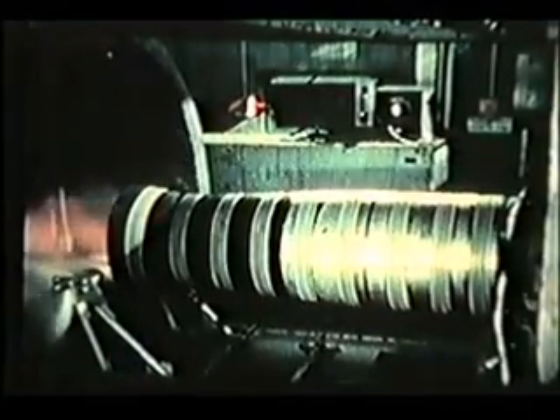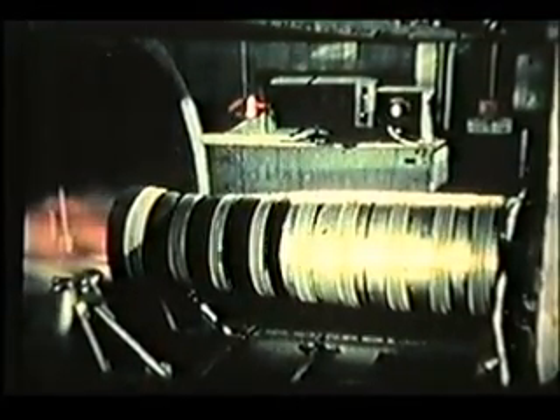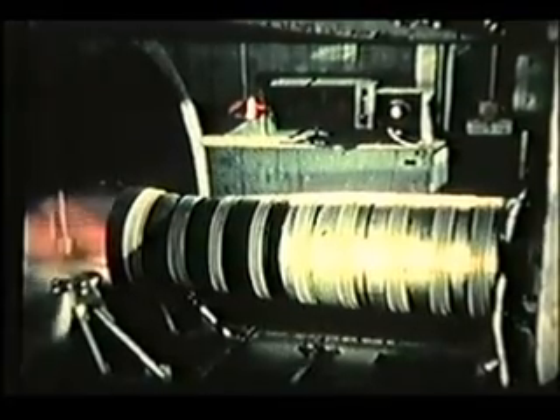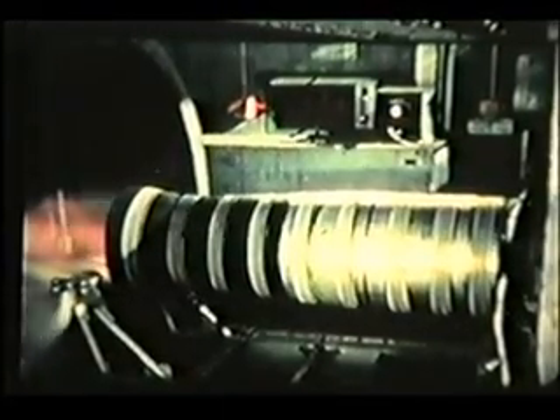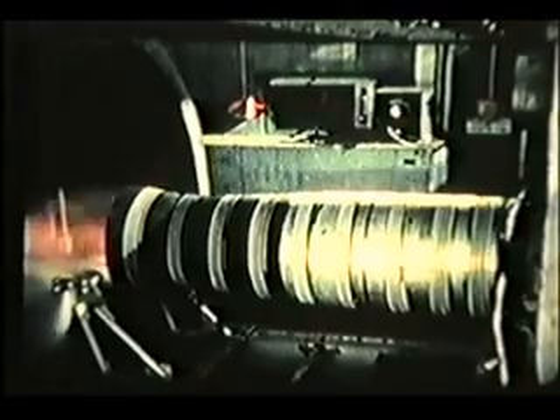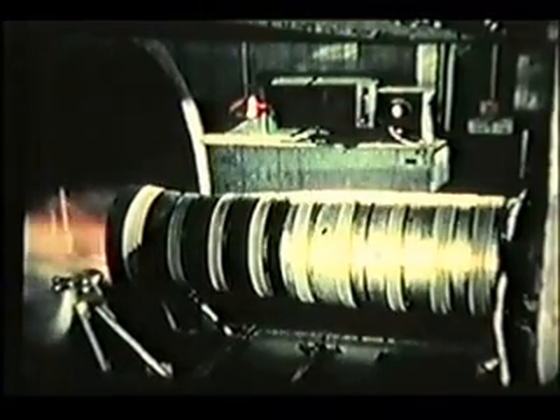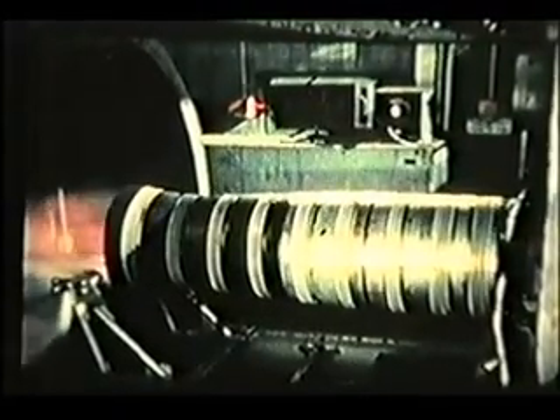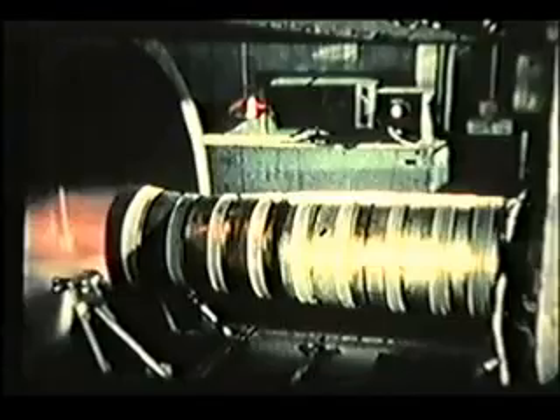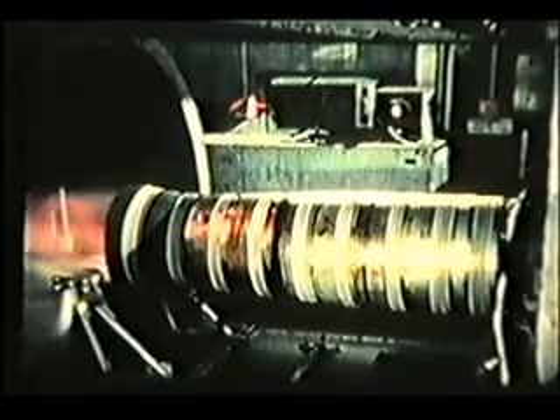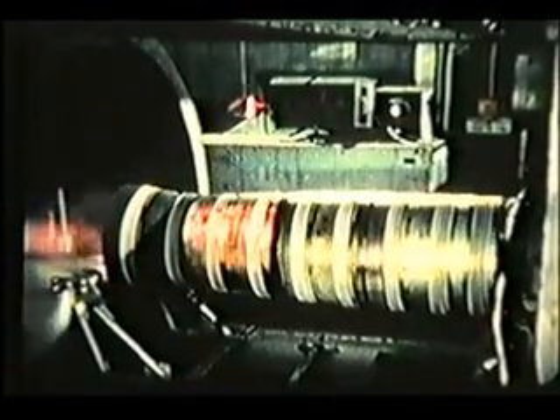In the right half of the ramjet has been coated in the light blue area, while the left-hand end, showing dark blue, is uncoated. Although the heat penetrates the bare metal, the coated area is effectively insulated and successfully withstands the vibration and erosive forces of the gases. Today, ramjets such as the Talos are protected with Rokide Z and nickel chrome undercoatings, and substantial increases in flight time are possible.